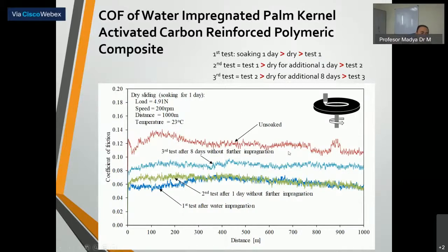We can see this is the datum. This is the first test, under water lubrication, and then this is the second test. We can see that there is not much difference in the coefficient of friction. But after the third test, which means after 8 days without further impregnation, we can see that the coefficient of friction is increased. This might be due to the evaporation of the water in the air. It means that the sample does not have enough lubricant because of the water evaporation.